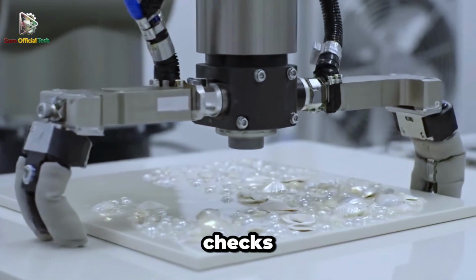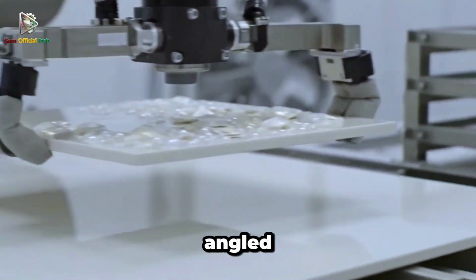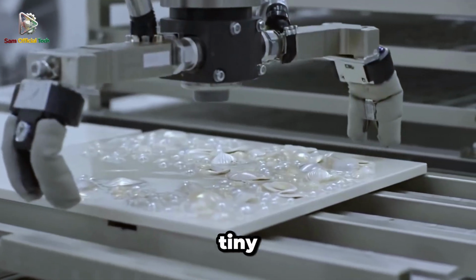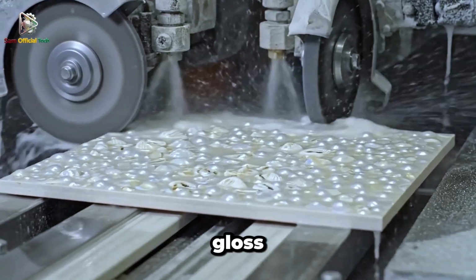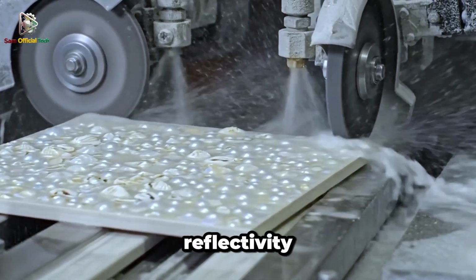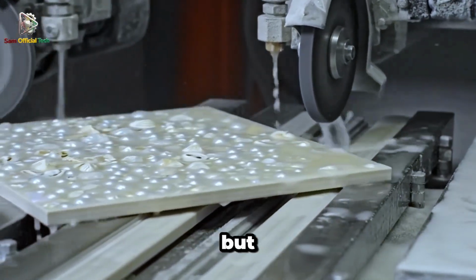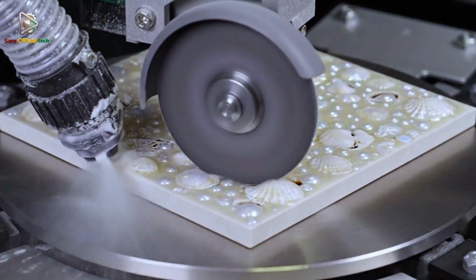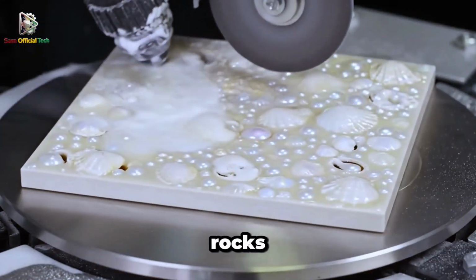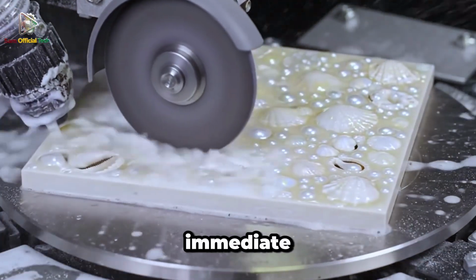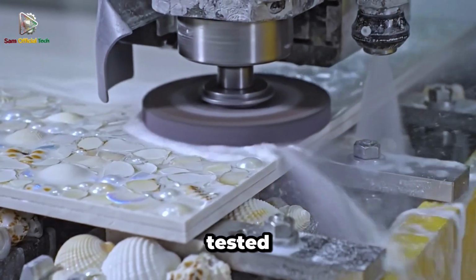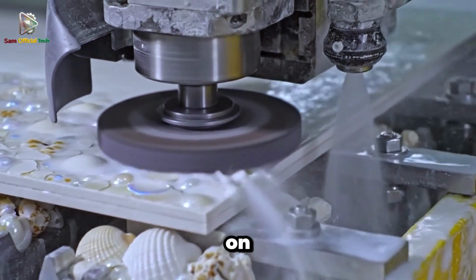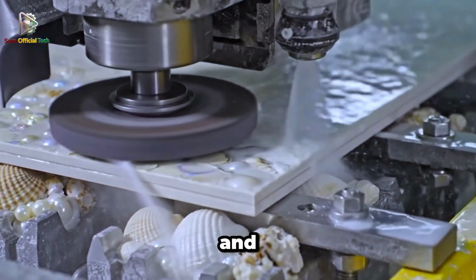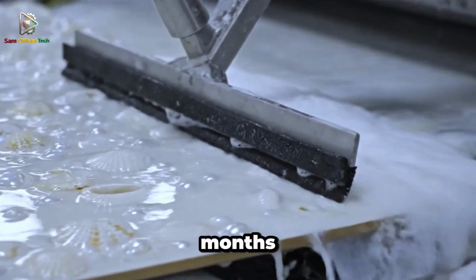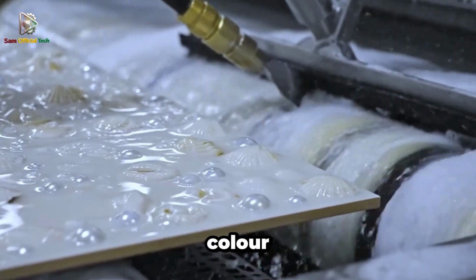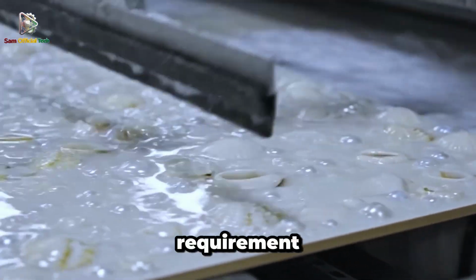Quality control is continuous because the defect modes are predictable. The factory checks for voids with visual inspection under angled light, because voids show as tiny black pinholes. Gloss meters quantify surface reflectivity, because looks shiny is subjective, but gloss units are measurable. Flatness is checked because a table that rocks on a flat floor is an immediate reject. Adhesion is tested with crosshatch or pull tests on sample panels to ensure shell and substrate bonding won't fail after months of temperature cycling.